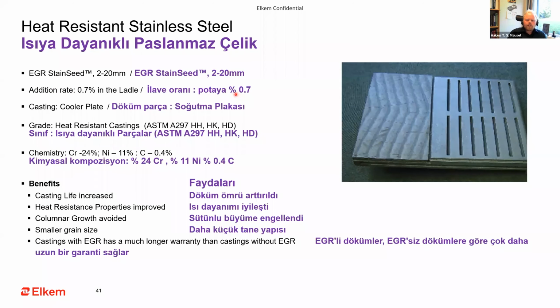Then we go into the heat-resistant stainless steels. So this is from a customer. They use the EGR stain seed 2 to 20 millimeter, and they add 0.7%, so 7 kilograms per ton of steel. What we see here is cooler plates, and they make these in the ASTM A297, the HH grade, the HK, and the HD grade. So typically the chemistry we see here is 24% chromium, 11% nickel, and 0.4% carbon. Of course these stainless grades are really high in carbon compared to other stainless grades.